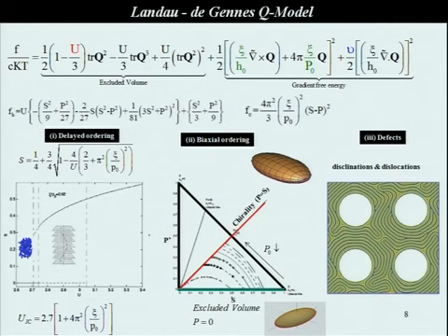And the other important point is, some people say, well, who cares about chirality? I do my Onsager with electrostatics and flexibility, I'm okay. But the other point is you're missing the effect of this pitch, P0. If you take this simple free energy and say, okay, I'm going to forget about biaxiality for the moment, I still pick up a P0 from this part, and the key point then is the pitch delays ordering.